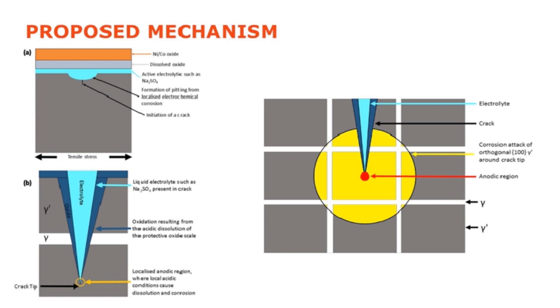And then the image on the right, I suppose, is me trying to theorize as to why we see corrosion cracks or corrosion driven cracks propagating on orthogonal planes or the cube planes, rather than where we would typically see them on the slip planes, the 1-1-1 octahedral planes. And I think that's because if you take a point at the crack tip where you have a localized anodic region and you grow that out, you can see that the gamma prime phase, which is kind of preferentially interacted with from that point, is all orthogonally located from that crack tip. So that's my theory as to one of the reasons why we see this preferential orthogonal growth and propagation occurring.